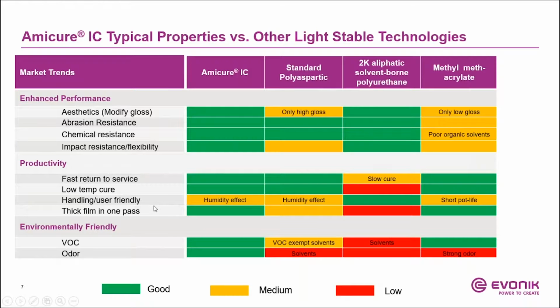Handling user friendliness. In this case, I have the polycarbamide technology in orange with polyaspartic. And the reason is really humidity effect. Humidity and temperature can affect the cure time. So really, humidity can shorten the pot life, especially high humidity. MMA, same thing in terms of you need an accelerator to kick it off, and sometimes pot life is very important. And because it's fast cure, you don't have a lot of time to work with the material. Urethanes tend to be a slow cure, and that also means it has longer open time. So I have it in green.